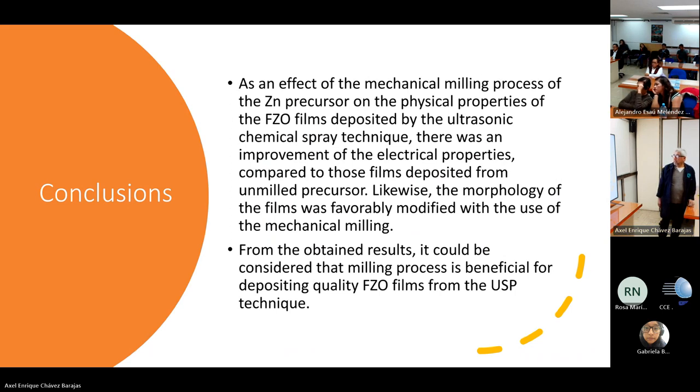Conclusions. The mechanical milling process is beneficial for the deposition quality of zinc oxide and fluorine doped zinc oxide films with a fresh solution the same day, avoiding the need to wait 1 to 2 days or perhaps 1 week in order to get quality films. This is the main contribution in our case, but this can also be applied to other films for applications such as photocatalysis, gas sensors, and others.